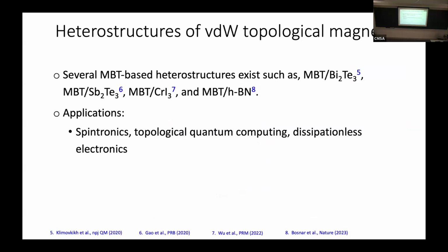We played a similar game. We looked at manganese bismuth telluride for one layer, bismuth telluride for another layer, and we would then change the chemical composition of the different sites, do some DFT calculations on a small set, and try to predict on a much larger set of materials using our AI tools. And these materials are also important for applications in spintronics and topological quantum computing and dissipationless electronics.